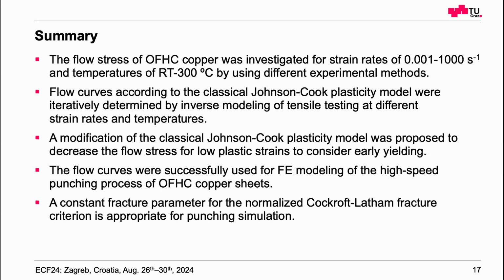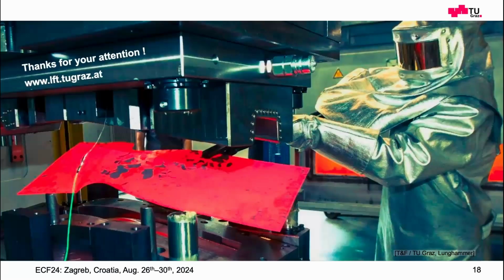So, a short summary. The flow stress of this copper was investigated for strain rates from quasi-static to 1000 per second and a temperature range from room temperature up to 300 degrees. The flow curves according to the classical Johnson-Cook plasticity were iteratively determined by inverse modeling. A modification of the classical Johnson-Cook plasticity was proposed to decrease the flow stress for low plastic strains, to consider this early yielding. And the flow curves were successfully used for FE modeling of the high-speed punching process for these copper sheets. We used a constant fracture parameter for the normalized Cockcroft-Latham fracture criterion, and this is appropriate for punching simulations. So thank you very much, and I'm open for questions.